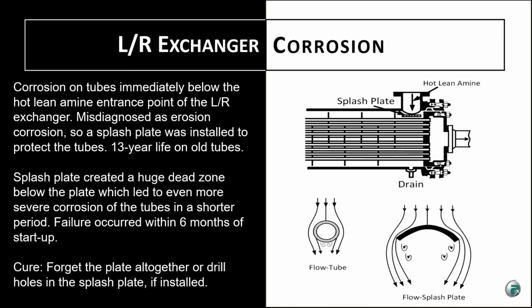Now, when we looked at the original tube bundle, the corrosion damage on the tubes was the underside of the tubes, not the top part of the tubes. So since it was on the underside of the tubes, we really wouldn't expect erosion. And what we determined was that the pitting on the bottom part of the tubes was caused by the flow effect around the tubes of that hot lean amine. There is an entrance condition, we break out acid gas, and the acid gas finds a dead zone, which happens to be the underside of the tubes. By welding that splash plate, they created a massive dead zone underneath the entrance. So rather than just destroying the underside of the tubes, they had severe damage over almost the entire tube sheet below the entrance.